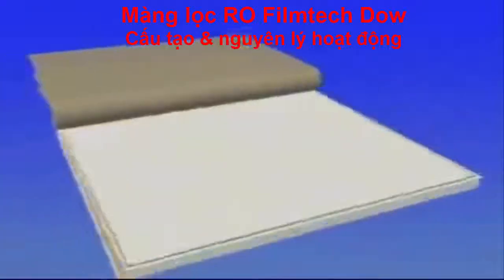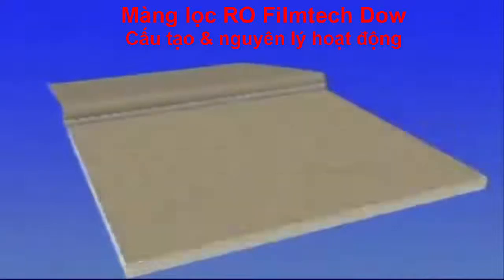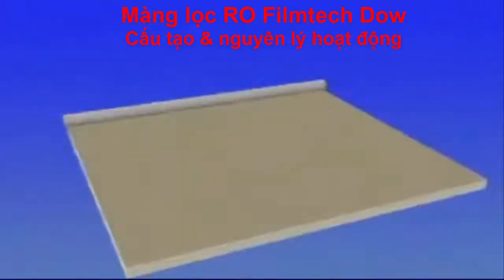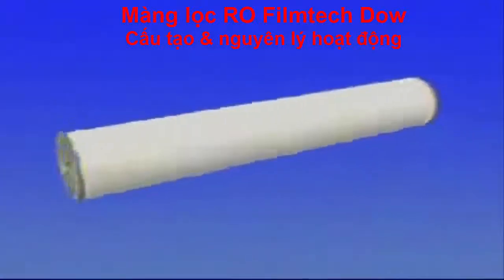The folded leaf is mechanically inserted between permeate carrier sheets. Successive membrane leaves are assembled and inserted between permeate channels, with glue lines between adjacent leaves forming a three-sided envelope enclosing the permeate carrier.